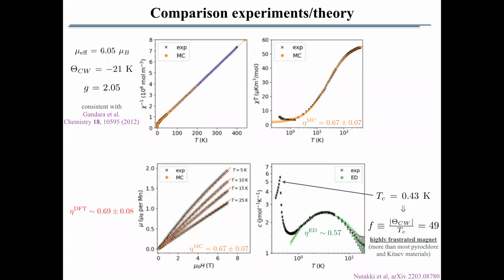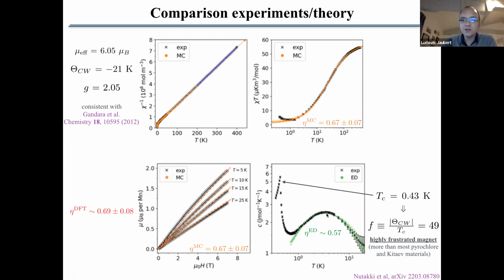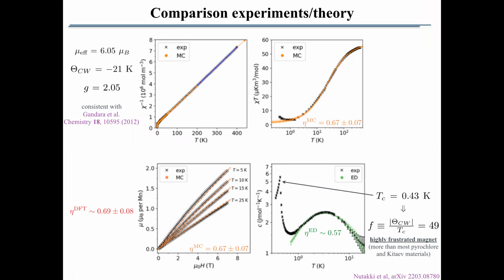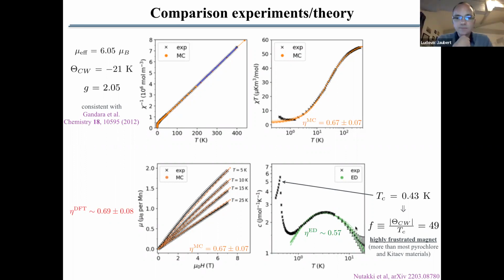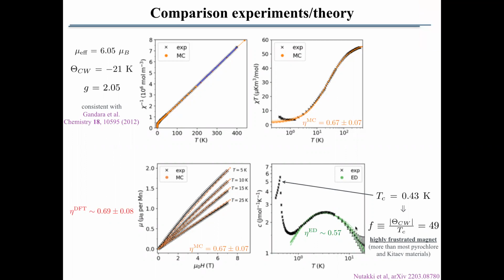But I thought based on what you plotted here, the system is actually in the paramagnetic state, right? I mean, if it was very strong electron correlations, in the paramagnetic state, the magnetism can contribute to heat capacity as well, right? I mean, since you don't really know what happens at the 0.43 Kelvin, what sort of magnetic phase transition it is, yeah. So I'm puzzled. So this one is not a phase transition; it's just a bump, so it's a crossover. I know, it's not a phase transition, yeah. But when you have spin fluctuations, when you have a very strong magnetic order, even in the paramagnetic state, you can have very strong spin correlations, right? The strong spin correlations may have strong temperature dependence that can contribute to your specific heat. I mean, it's hard for me to believe, with a spin of 5/2, you have such a quantum effect.